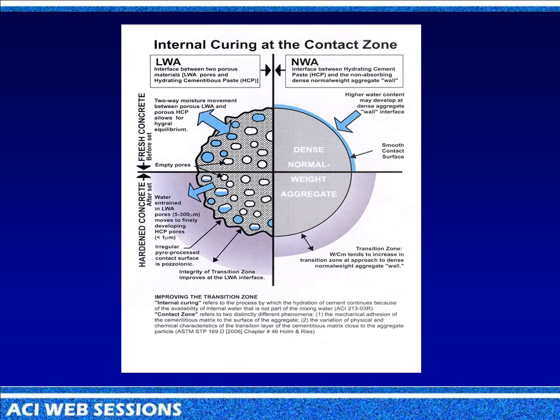Now this is a little bit complicated, but not that complicated. The one on the right, this whole half is normal weight concrete. This whole half over here is lightweight concrete. And the top half is when it's fresh concrete, and the bottom half is when it's hardened concrete. Well, if you look up in the right corner, what you're seeing up here is this is a normal dense concrete. The water comes to it, and it builds a water lens on the aggregate. And then you get this transition zone afterwards. It's not that big, but some cases, if you add silica fume and whatnot, it makes this transition zone a lot better. Now, in contrast, over here with the lightweight aggregate, you don't get that water lens.